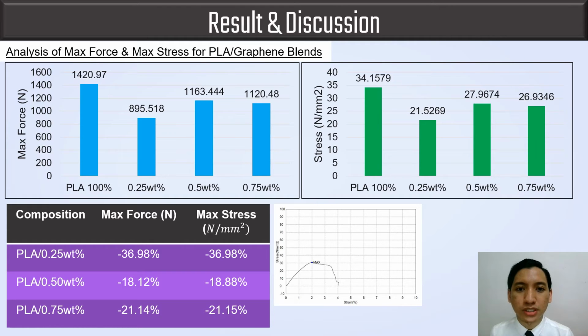In the case of the PLA graphene blend, Table 2 shows a significant reduction of tensile strength of the blend nanocomposite. The addition of 0.25% graphene in the blend results in a decrease in tensile strength of up to 36.98%. However, a further increase of graphene to 0.5% reduces the tensile strength by 18.12%, which is half of the value of tensile strength in the 0.25% graphene in PLA blend.